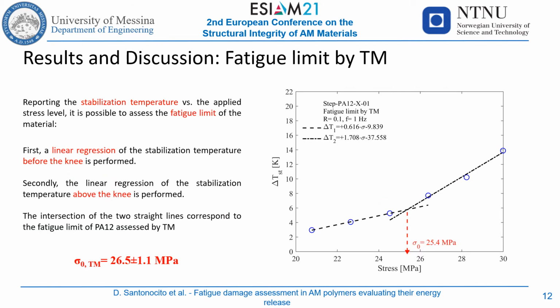If we report the different stabilization temperatures versus the applied stress level, it is possible to observe two linear trends with different slopes. The first linear trend is typical of stress levels below the fatigue limit of the material and can be attributed to noise in the temperature signal or material damping, while the second is characteristic of energy release due to fatigue damage phenomena. By the intersection of the two linear trends, it is possible to assess in a very rapid way, even with one specimen, the fatigue limit of the material.